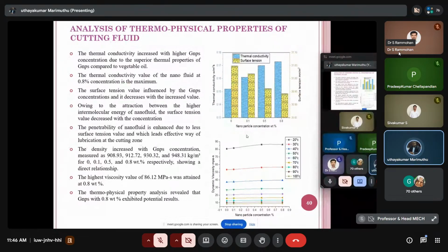The thermal conductivity increased with a higher GNPs concentration due to the superior thermal properties of the GNPs compared to vegetable oil. The thermal conductivity value of nanofluid at 0.8% concentration is the maximum. The surface tension value is influenced by GNPs concentration and it decreased with increased value. Owing to the attraction between the higher intermolecular energy of nanofluid, the surface tension value decreased with the concentration.